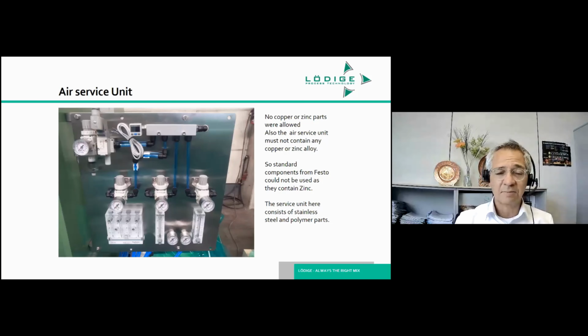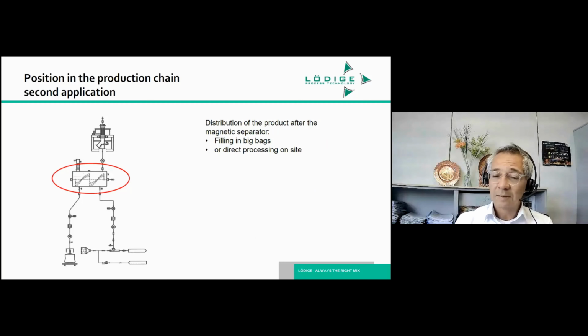But this is going back to standard. But if you look at how the air is treated, okay, you have an air control system where incoming air is reduced in pressure for the seals, the airflow rate is regulated, and so on. But standardized items appeared to have metals or materials which are absolutely not allowed in battery masses, and this is copper and zinc. So if minor amounts of iron are allowed, copper and zinc are an absolute no-go. So we had to redo again also the air service system, ending up with making everything all stainless steel or polymer based. And again, a key feature when looking into mixing equipment is looking into the auxiliaries, and this air treatment is one of them. That was the first mixer.